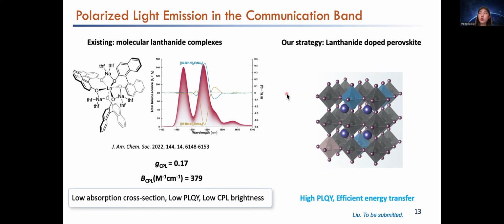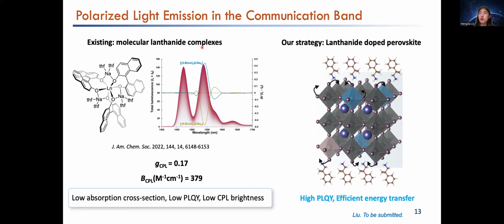So our strategy is we think if we can use perovskite as an energy transfer matrix to replace this lanthanide complex and dope the perovskite with the lanthanide dopants. And if we can put the chiral molecules on the surfaces, the chiral molecules can further distort the surface structure. So the lanthanide dopants can be located in a distorted chiral environment. This will mimic the structure or the mechanism of the molecular lanthanide complex. So if we shine light on the material, there is a very efficient energy transfer from the perovskite matrix to the lanthanide dopant, and it emits light from the lanthanide dopant.